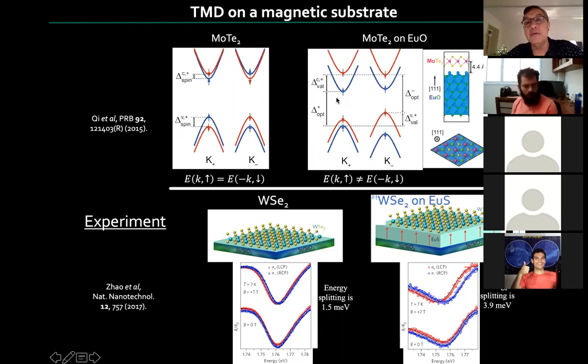So you will see that here on the right, that's what has happened, right? The spin down has moved up, the spin up has moved down. And here the same happened, except that they crossed each other. And the end result, the same with the conduction band, is that you end up with an effective band structure on one valley that is different from the other. You've broken time reversal symmetry, of course, because there is an applied field. That gives you different, if you're interested in the bulk optical properties, for left and right circularly polarized light, a different resonant frequency. Sorry, a different excitonic absorption.